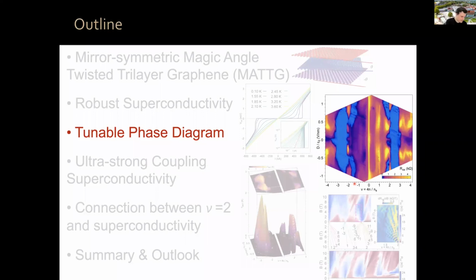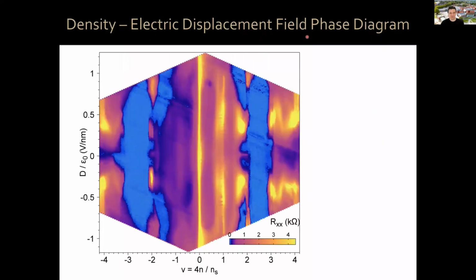Now, the system is extremely tunable, much more than the bilayer case, actually. So we have now these two independent knobs, charge density and electric displacement field. This is what the resistivity in the color scale looks like as a function of displacement field, divided by epsilon naught, on this vertical axis and filling factor on this axis.